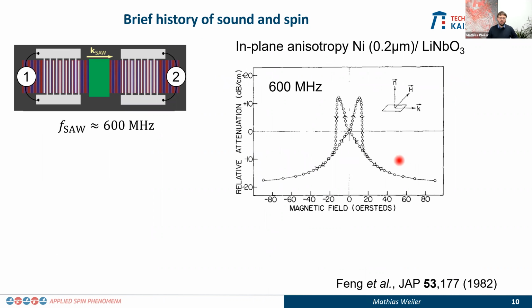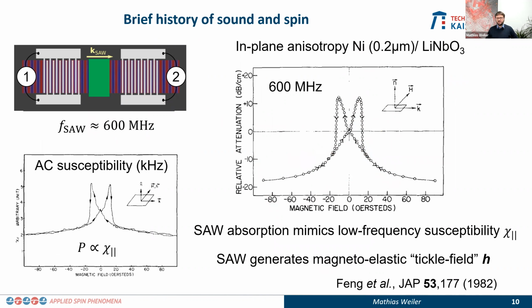One can then go on, and there are experiments a bit later that showed, well, indeed, if one increases the frequency of the acoustic wave a bit, one can basically use the magnetoelastic field as what they call a tickle field to measure the magnetic hysteresis of such a nickel film. And they showed that their experiments recorded in the surface acoustic wave spectroscopy closely mimic what they do in a standard AC susceptibility measurement of the same nickel film, right? So they established this idea that the surface acoustic wave really generates such a magnetoelastic field as predicted by Kittel.